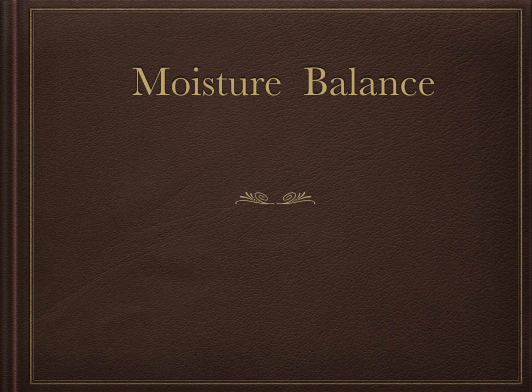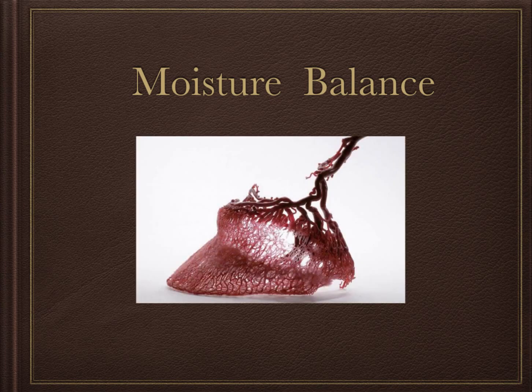So we know that feet in a wet environment swell up, they expand, and all the connections get a little weaker from that expansion. In a dry climate, feet get hard, compact, tight, and usually pretty durable. A lot of people don't realize where moisture comes from, and actually very, very little moisture in the horse's foot comes from the environment. It comes mostly from the blood supply. 90% of it comes from circulation in the foot, which is why circulation is so critical in the foot, because if you starve a foot from circulation, not only does blood circulation produce all the tissues of the foot, but it also hydrates the foot.